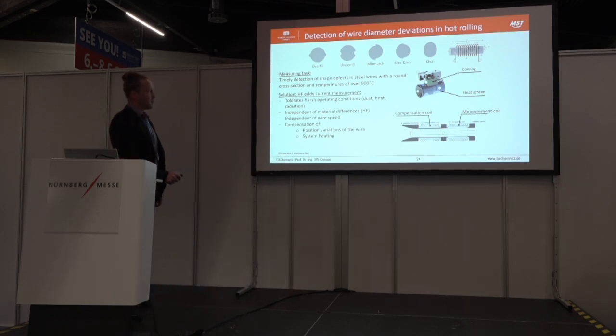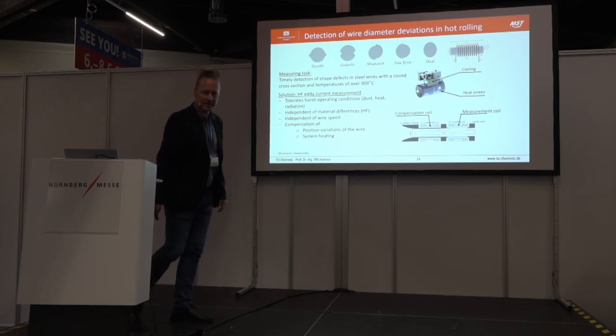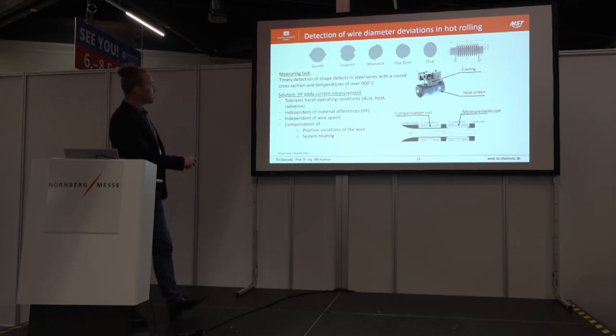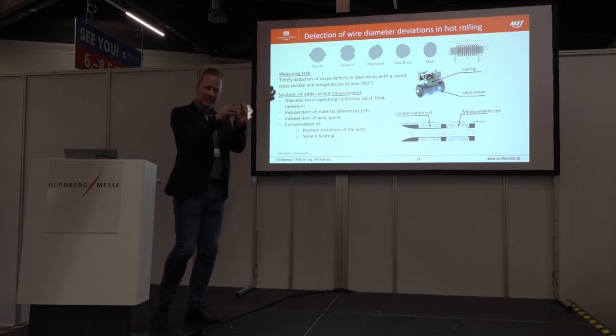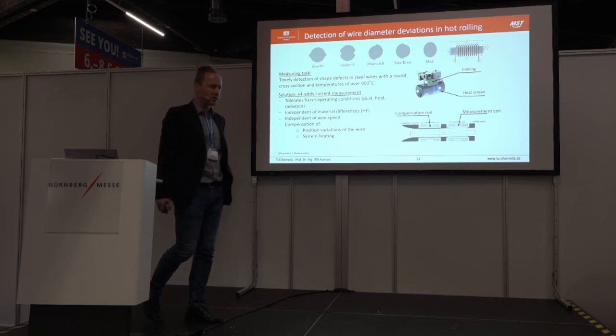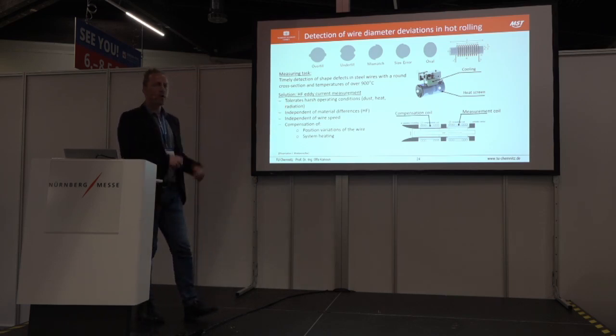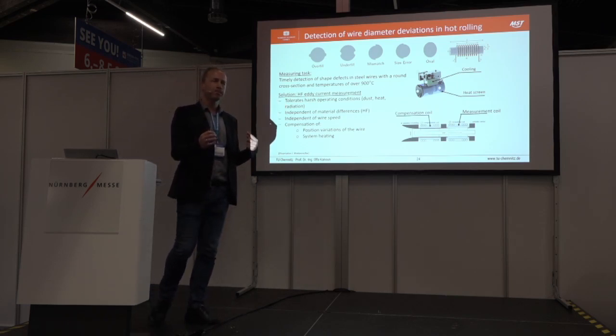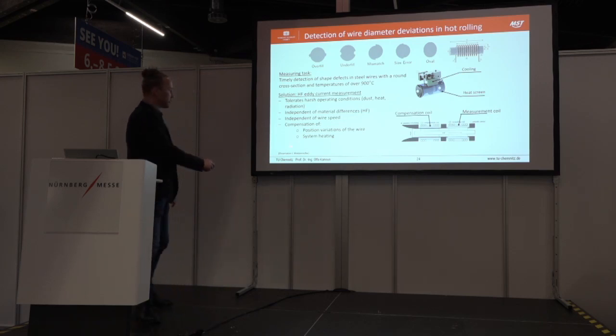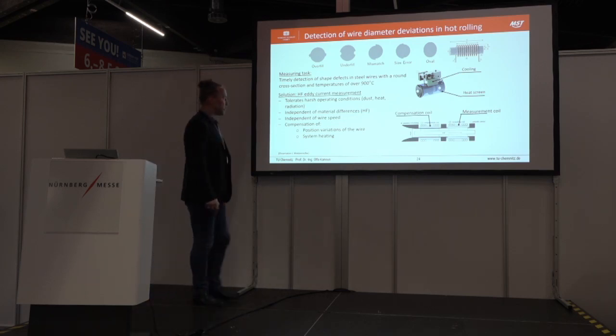In that case, we also apply a coil, an inductive approach, working at up to 900 degrees. So a cooling system is also included, and we are able to identify such shapes. We were simply detecting the shape structure of this rod, and what you can see here are examples of failures caused by process parameters in the process. If you like, you can read it in a dissertation from our team.